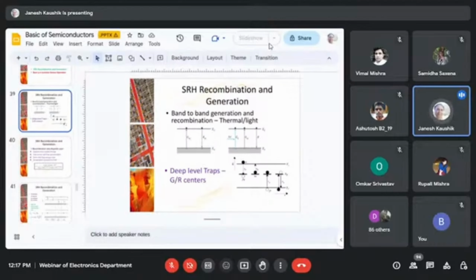So when it is a trap, or when it is a generation recombination center, that depends upon the probabilities, what is the rate of generation of the carrier from that particular energy level, or what is the recombination rate. So it can capture, if you see the lower diagram, an electron from the conduction band, or it can capture a hole from the valence band. It can emit an electron to the conduction band, or it can do the emission and capture simultaneously with either the valence band or the conduction band. So we calculate rates here, capture rates, because this is not a single phenomenon; it's a statistical phenomenon. So there are capture rates, there are emission rates, and there is a recombination rate.